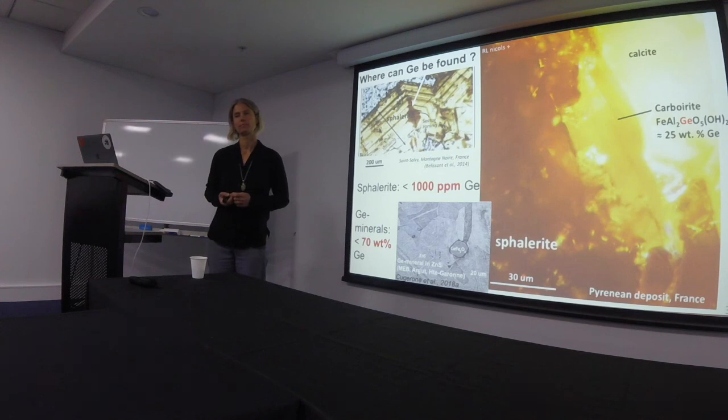You can mine things, like the current MacArthur River work. They were floating it down to 7 microns, which was a challenge, and it didn't work very well, but they fixed that up. So you can do 10 micron stuff, but the concentration of germanium would never justify commercial extraction. You'd have to take the zinc out separately, process it separately. And the germanium price, while it is essential in modern electronics, is simply not high enough to justify a commercial operation. It just wouldn't work.